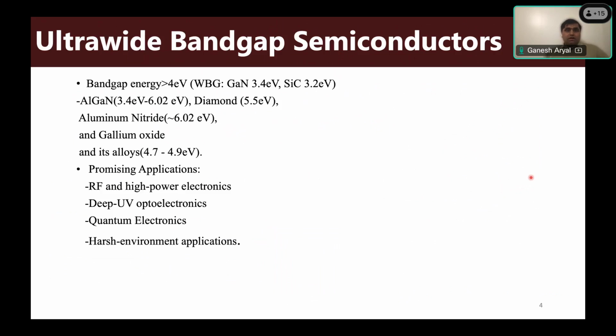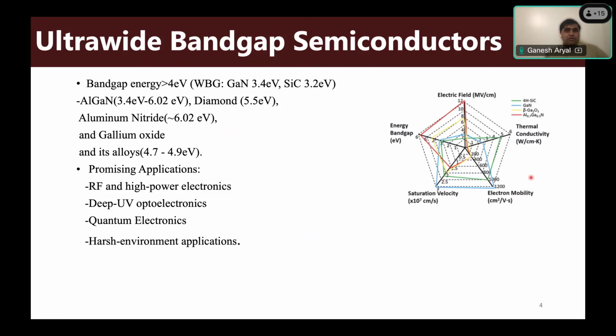Now let's talk a little bit about ultra wide bandgap semiconductors. Those semiconductors which have a band gap usually greater than 4 electron volts are called ultra wide bandgap semiconductors. For instance, aluminum gallium nitride has a band gap that varies from 3.4 electron volts to 6.02 electron volts, depending upon the aluminum content in the gallium nitride. So we can say that aluminum gallium nitride has a tunable band gap. Diamond has around 5.5 electron volts band gap, whereas aluminum nitride has around 6.02 electron volts. And gallium oxide is also called an ultra wide band gap semiconductor.